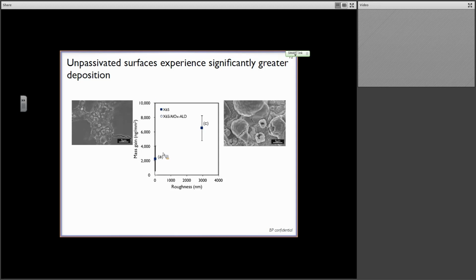So once we have taken our specimens and put them in our autoclave and done our fouling, we weigh them before and after. And so that is a measure of the relative amount of fouling or deposition that we have on our specimens due to the interaction of the carbonaceous materials. And so what you can see here is that, sorry, I think I lost my labels, but this micrograph up here corresponds to this data point here labeled as A.